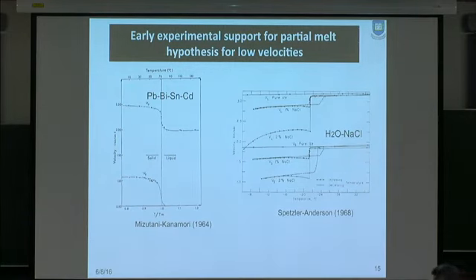And if you look at the history, there are a couple of papers published about 50 years ago, a time most of you were not born. This is the Kanamori paper. This is the year in which he got his PhD. So Kanamori's PhD must be a mineral physics PhD. He did measurements of the velocities in those alloys across the melting, partial melting, and found that even a small amount of melt could reduce the seismic wave velocities dramatically, 10% or so. 4 years later, in the US, Spetzler and Anderson did very similar experiments, with ice and sodium chloride, finding that even a small amount of melt could reduce the velocity 10% or so, very dramatically. Those gave us the feeling that a tiny amount of melt is enough to create low velocities.